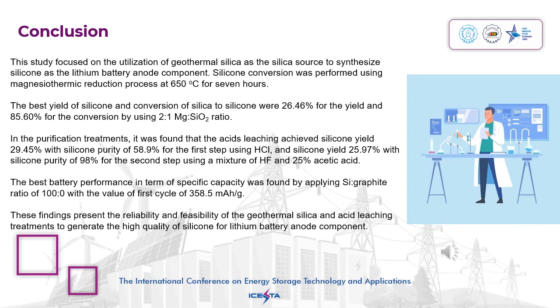In the purification treatment, it was found that the acid leaching achieved a silicon yield of 29.45% with silicon purity of 58.9% for the first step using hydrochloric acid, and a silicon yield of 25.97% with silicon purity of 98% for the second step using a mixture of hydrofluoric acid and 25% acetic acid.